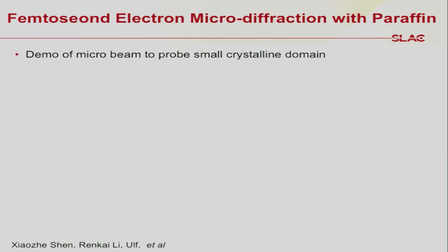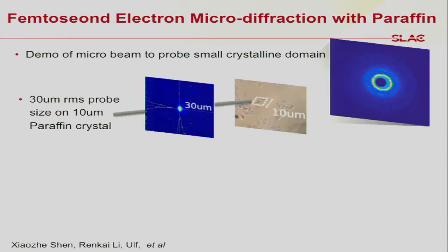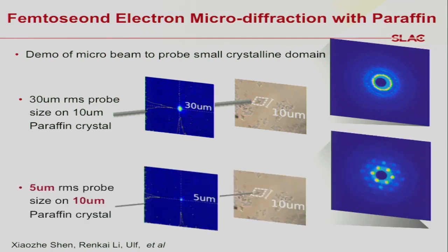So I want to quickly show you the latest experiment result that we call microfocusing. In this experiment, we basically look at an organic paraffin molecule. The crystal size is about 10 microns. So when we have an electron beam of about 30 microns, we get this ring-like diffraction structure. This is what people usually call polycrystal type. As we decrease our electron probe from 30 to 5 microns, we have a high-quality single-crystal diffraction.